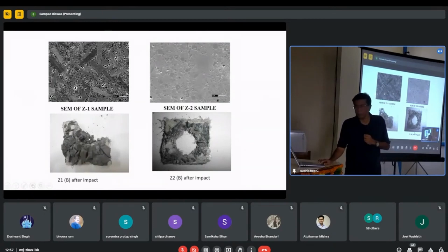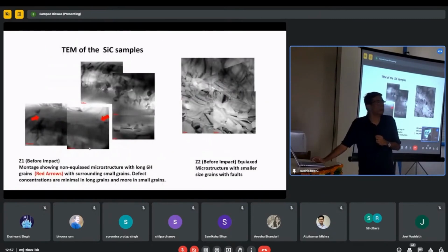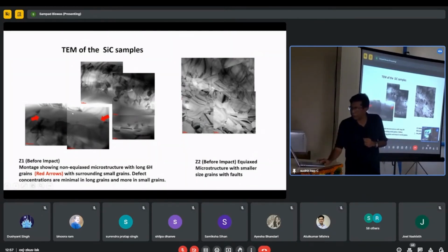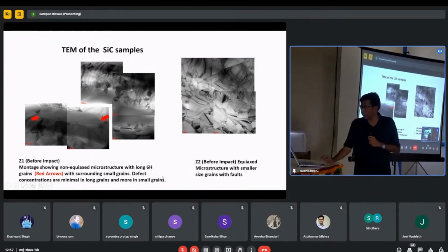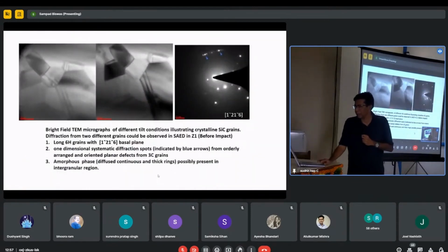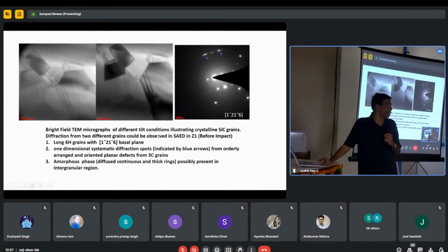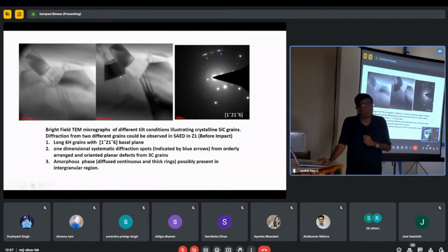So we took out the fragments near the bullet hit region, and we then carried out sections for the TEM analysis. In this TEM analysis, you can find this is a very long grain I wanted to show you, and these are very small grains attached to it. In the other case, it is very small grains. What I wanted to show you is that the surrounding small grains are also very important. They have a lot of defects, and these defects have been analyzed here. This is a bright field TEM micrograph under different tilt conditions to reveal the microstructures more efficiently. And this is the SAED pattern.